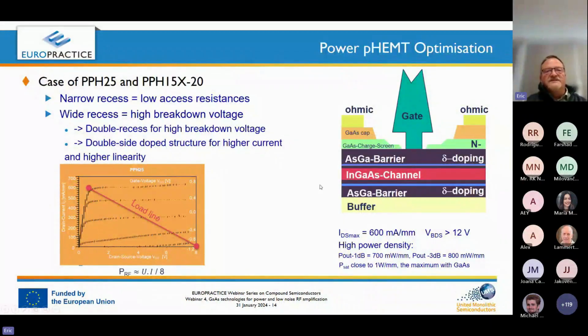This is a way we can optimize both the power density and also the linearity, because for these power amplifiers, what is important also is to keep as much as possible a good linearity. So with GaAs, typically what we can do is to achieve something like 600 milliampere per millimeter at the transistor level, with a typical breakdown voltage higher than 12 volt and a high power density. We say, generally speaking, that PSAT, so saturated power, is close to 1 watt per millimeter on GaAs, where for the GaN technologies, that is another topic, we can reach 5 to 10 watt per millimeter.